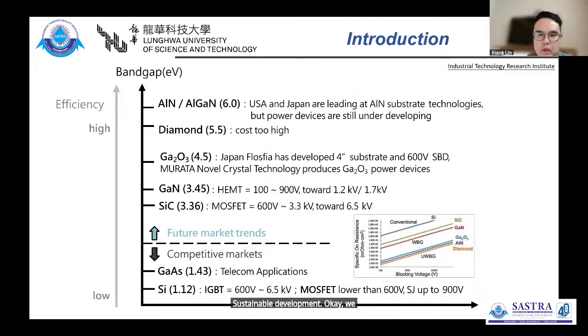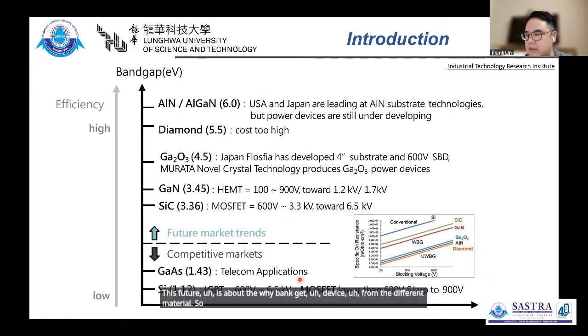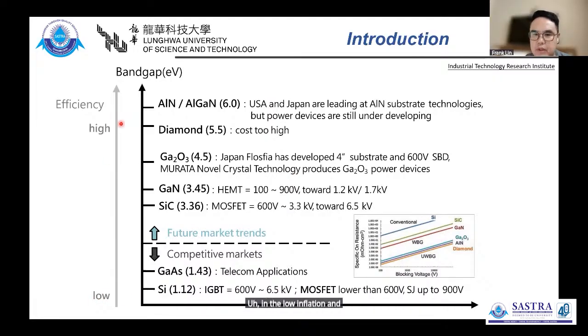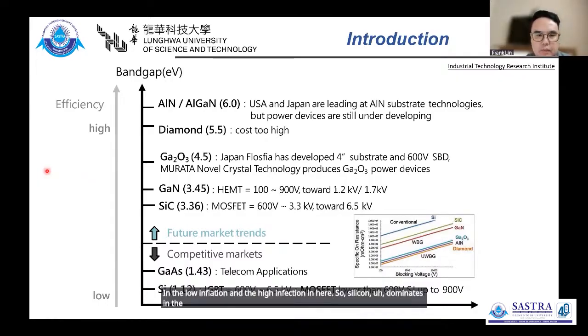Okay, this figure shows wide bandgap devices from different materials. We can see the low voltage and high voltage regions here. Silicon dominates in the market, supporting the development of the IGBT and the super junction MOSFET. However, silicon has already reached its physical limits in terms of efficiency and breakdown voltage. So gallium nitride and silicon carbide have already achieved significant progress in the market. Gallium nitride is mainly used in the 100 to 900 volt range, moving toward 1.2 kilovolt and 1.7 kilovolt. Silicon carbide covers higher voltage from 600 volt up to 3.3 kilovolt, and is progressing toward 6.5 kilovolt, making it particularly suitable for high voltage and high efficiency application.